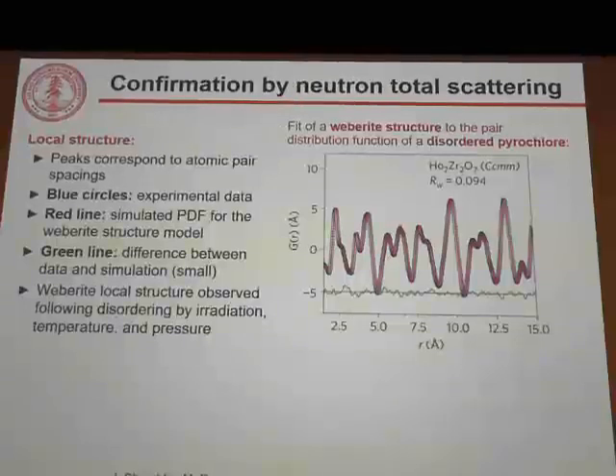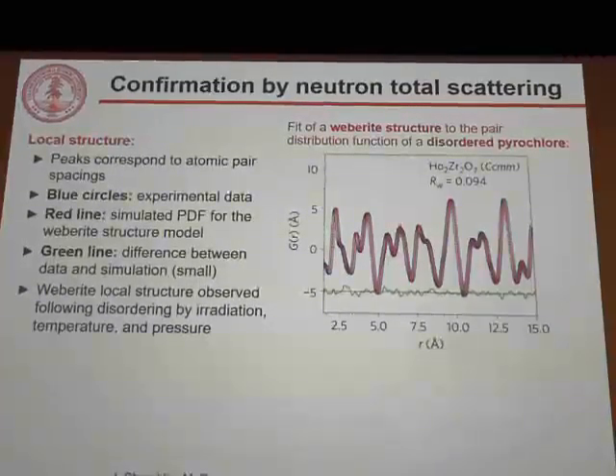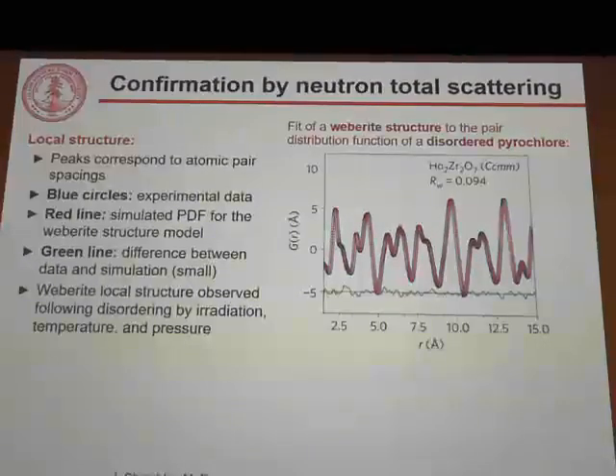And here I show blue circles, which are experimental data from a disordered pyrochlore, and then a red line showing a simulated PDF for a Weberite structure model, and we see the match is great. The green difference curve at the bottom is very small. So this confirms that a Weberite local structure is formed in all of these pyrochlores when we disorder them or amorphize them. And in fact, this same local structure is formed regardless of what extreme environment it is that is damaging these materials, if it's irradiation, if it's pressure, if it's high temperature.